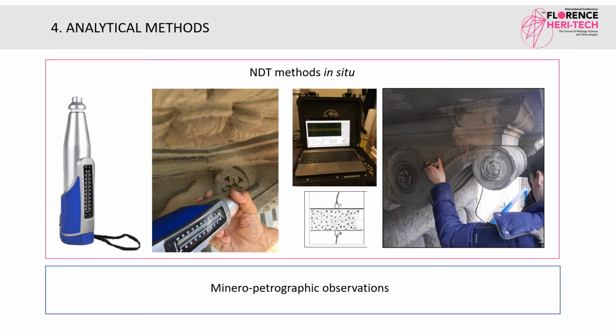Each corbel was analyzed in the inner, center, and outermost portions to verify the uniformity of the entire element. The ultrasonic and Schmidt hammer tests were performed at the same point of the surface, making a reproducible scheme of measure. Furthermore, mineropetrographic observations in polarized light microscopy were made in laboratory to investigate the sandstone decay and stone characteristics.